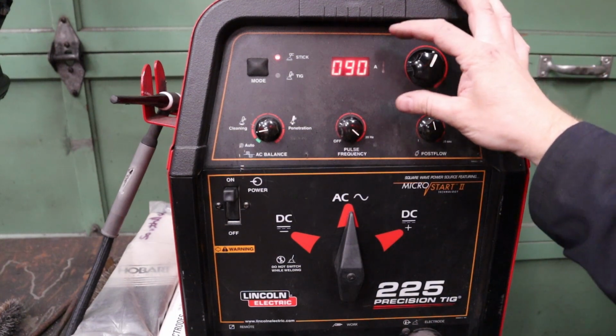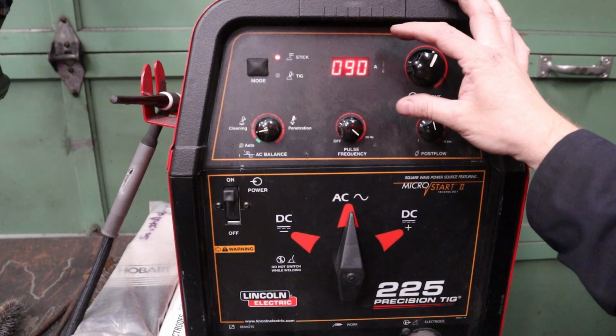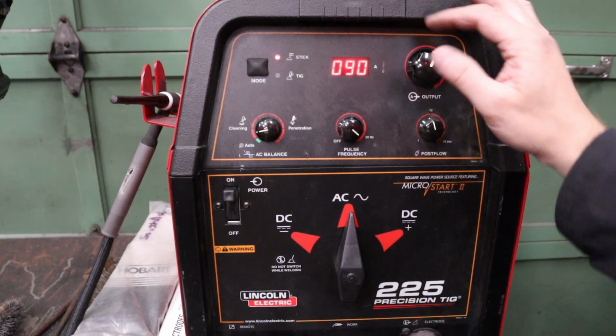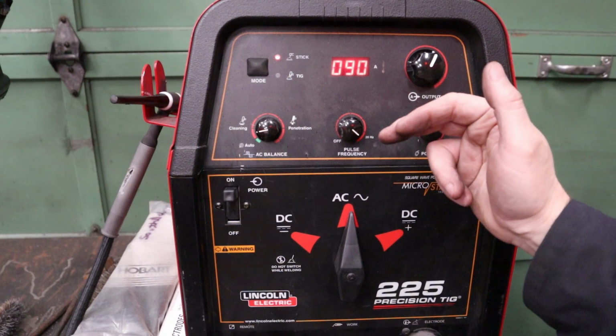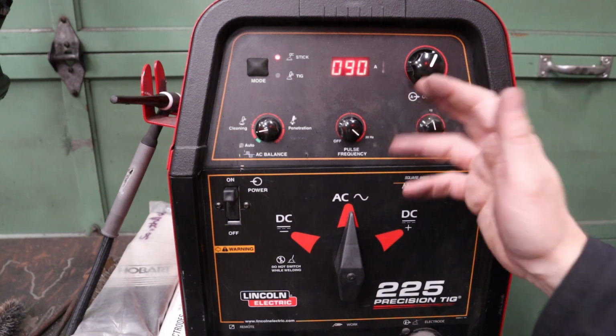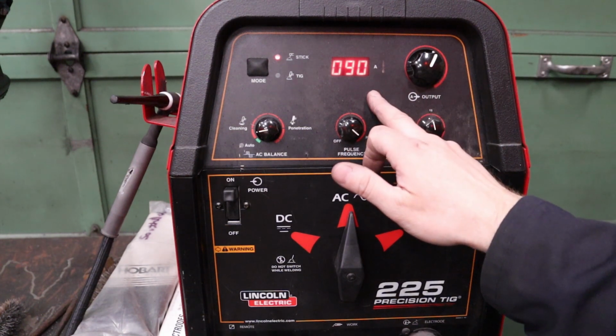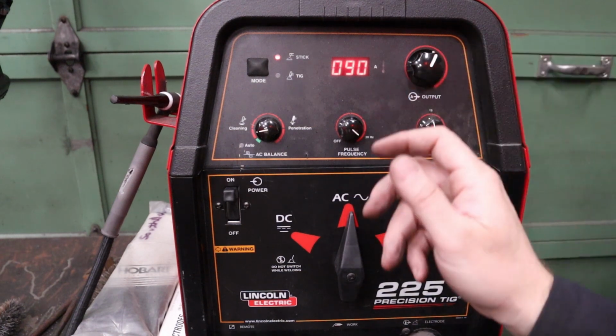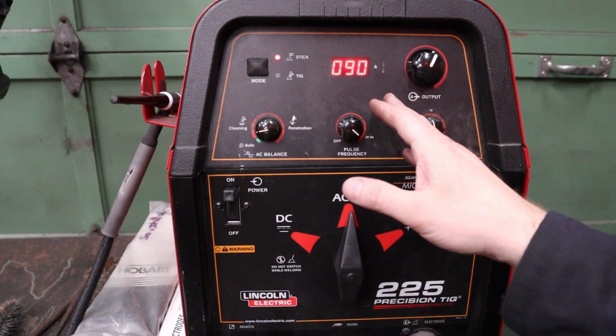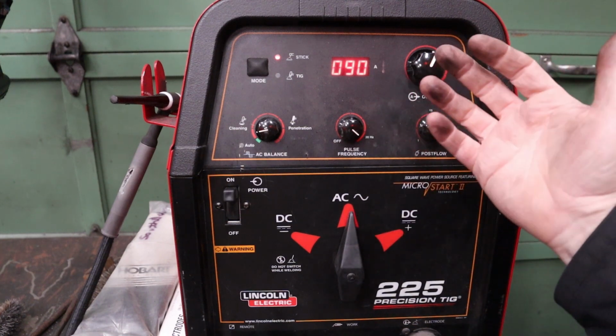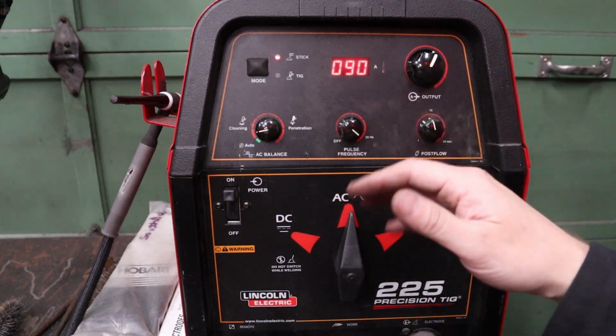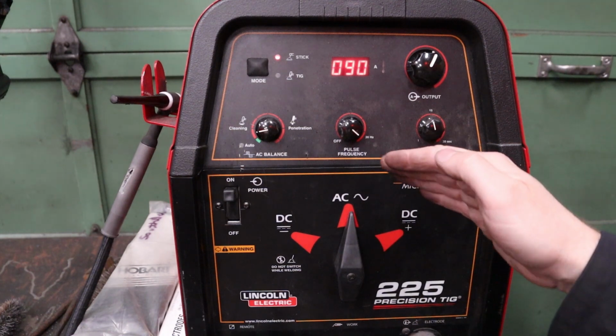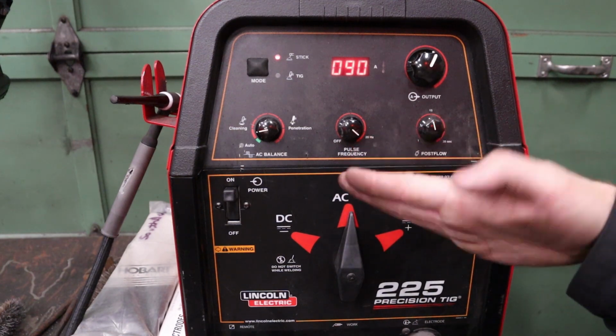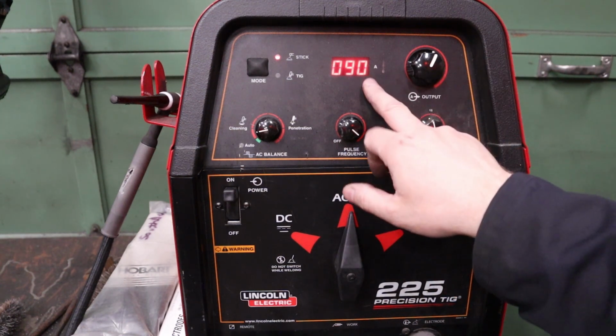Now, once you try these settings on a piece of scrap metal before you start, if you find that your electrode is sticking constantly to the metal and it's really hard to not do that, that's usually because your amperage is too low. So try turning it up a little bit and then trying again. And the other way, if it's too hot, you're going to find that you're blowing through your material, or instead of getting a nice kind of crowned weld bead, you're actually getting it flat or even concave and melting through. That's your amperage too high.